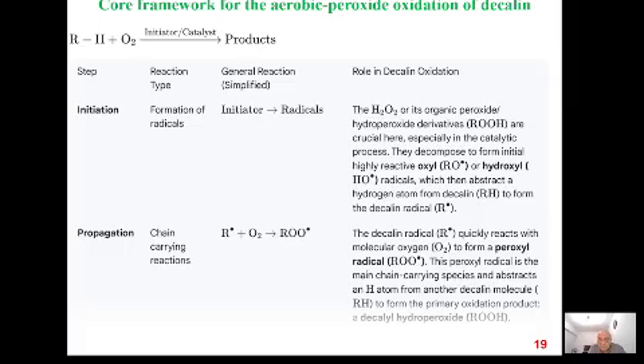Hydrogen peroxide decomposes to form initial highly reactive hydroxyl radicals, which then abstract a hydrogen atom from decalin to form a decalin radical. That is related to the mechanism of the oxidation. The decalin radical quickly reacts with molecular oxygen to form a peroxyl radical. This peroxyl radical is the main chain-carrying species and abstracts a hydrogen atom from another decalin molecule to form the primary oxidation product, and then the reaction goes to the stationary stage.